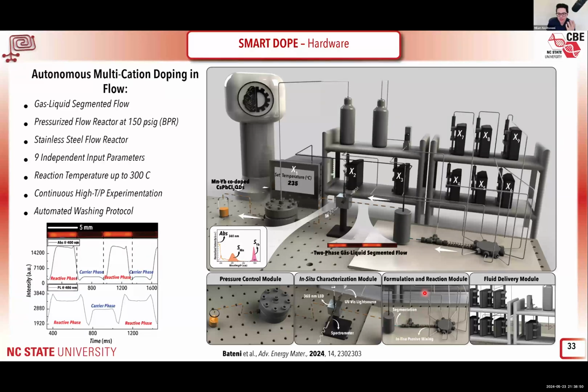So to tackle this challenge, we basically designed an autonomous fluidic lab with 11 inputs, and in this case, we have 2 outputs. And the synthesis in this case is a high-temperature synthesis. We have to go to temperatures as high as 300 degrees Celsius. So we use stainless steel flow reactors here, and we use a specific type of flow format called segmented flow. We have an inert gas and liquid. So this is gas-liquid segmented flow with argon, and we pressurize the reactor so we can have this very uniform gas-liquid segmented flow. The formulation happens here with all of your precursors, the mixing here, the gas-liquid segmentation happens here. So you have very good mixing inside each droplet as they move through the reactor. And then this is where we do spectroscopy to characterize the quantum dot synthesizing flow.